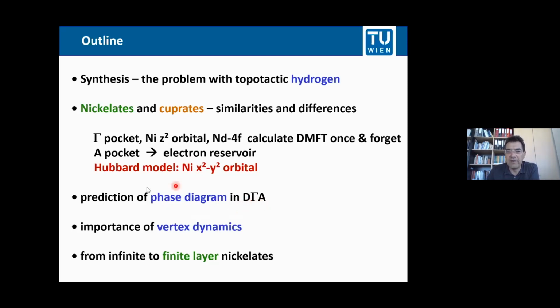We then also have done beyond DMFT calculations using the dynamical gamma vertex approximation. And we were even able to calculate the phase diagram before it was measured experimentally. And I will show you that these results are quite good. I'm very happy about that. And I'd like to discuss, if time allows, why for predicting TC well, you need to take into account the vertex dynamics. And our most recent results go into other nickelates, namely going from the infinite layer to a finite layer structure. Okay, that's the outline, and let's start with the synthesis.